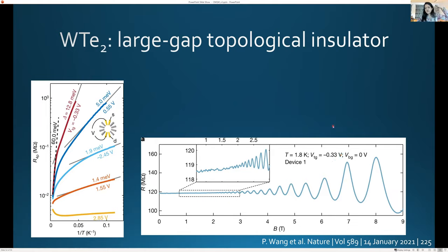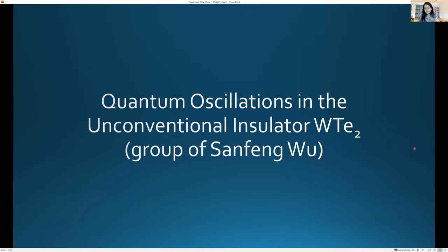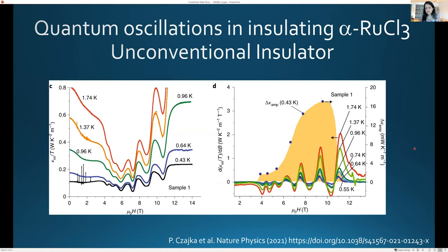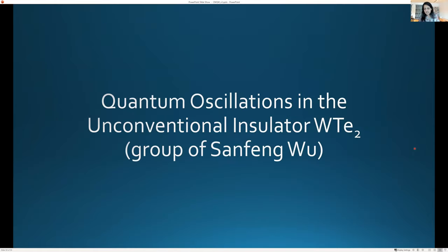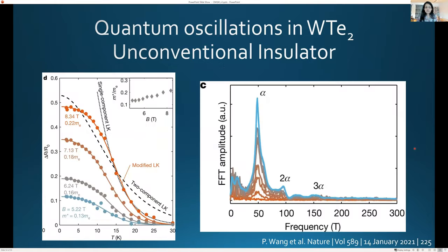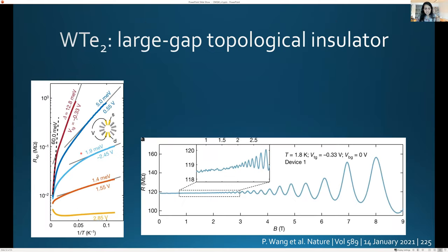So both in the ruthenium trichloride and this material, which is the tungsten ditelluride as well. I think in the ruthenium trichloride, one of the points that has been made is that the gap in this material is much bigger than a few meV. It's now like a few hundred meV. So this gapped argument for electrons jumping across the gap becomes even less tenable. So that's clearly not the explanation for the quantum oscillations. And similarly, in the tungsten ditelluride as well, the gap can be tuned to a fairly large gap, I guess around 60 meV.